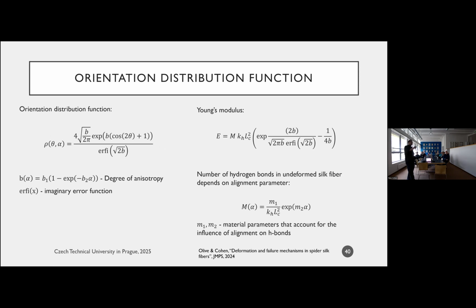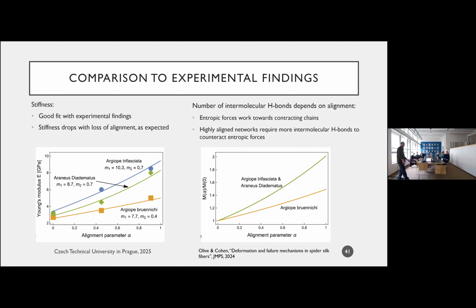Okay, and so before we can actually compare it, this is the orientation distribution function that we took. Run through the math, you can find out that this is what the Young's modulus looks like. This is what we assume would be the dependence of the number of intermolecular bonds as a function of the alignment parameter. And once we had all of these, we said that's perfect. Let's compare. And so we started comparing.